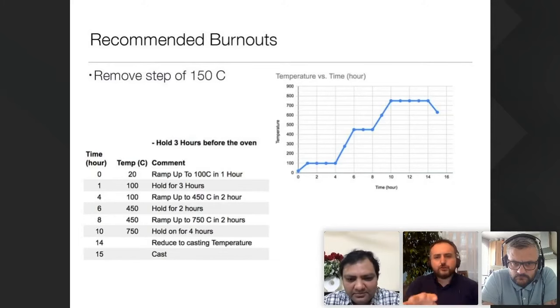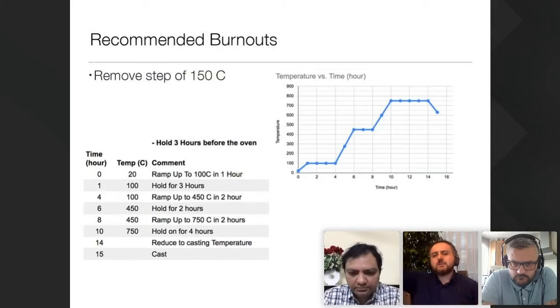From the resin perspective, there is no issue doing that. You can do it because the temperature, from 100 to 450 degrees, at least for our resin, has low expansion, so there's no major issue. For other resins, you may have issues doing that, I think. But as long as you arrive at 500 degrees, everything is gone - whether you do it fast or with a lot of steps, the step of 150 degrees doesn't change anything for the resin.